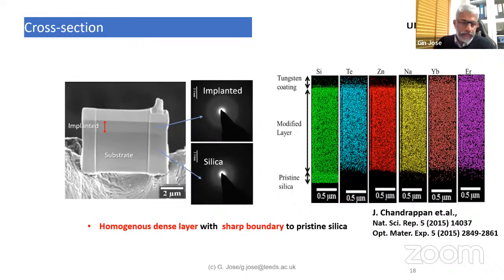Or doped into the glass. In order to assess how the doped material looks, we can take a slice out of this glass, like slicing a cake. Here we use what we call the focused ion beam to cut a slice from the surface of the glass. To get this out, you put a metallic coating at the surface, and the glass surface starts from here to there. That is the doped layer, the modified layer, and that's the original glass. So that we can analyze. We can produce this sample using focused ion beam milling, what we call FIB, and then you thin it down.